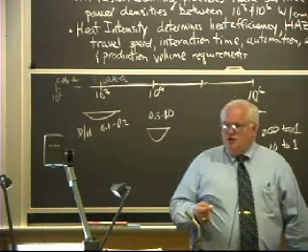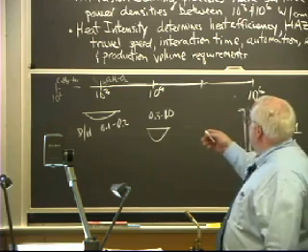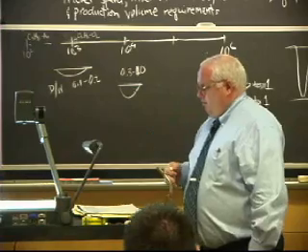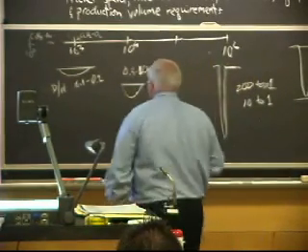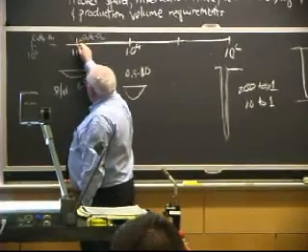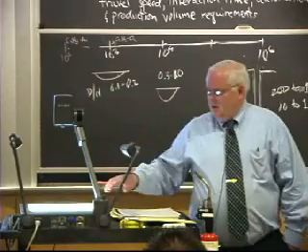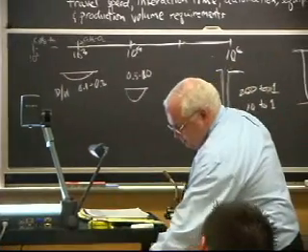Because I don't carry that nitrogen around, I get a higher temperature because I don't have all that nitrogen that I have to heat up. And we'll talk about these temperatures in a second. But in addition, because I get the higher temperature, I get a higher burning velocity, and that gives me a much higher combustion intensity. However, that's the rate I'm generating heat. But if I actually measure the heat flux to the surface, I only get 2 to 10% of that heat actually into the bulk of the material. And does anybody know the reason why we are so inefficient?